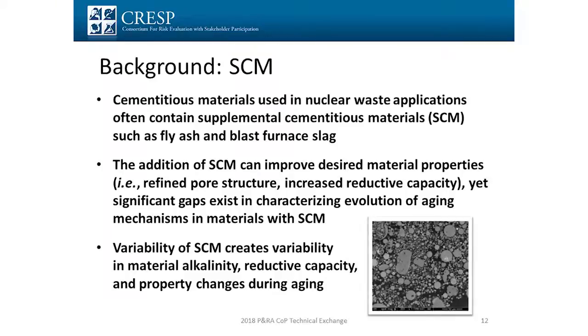So again, in terms of supplemental cementitious materials, often things like fly ash or blast furnace slag is added to change the properties of the material. Say if you want to increase the redox capacity of the material, you might add slag to affect things like keeping the technetium in the material. So the addition of this can be important in terms of how the oxidation and carbonation affect the material.